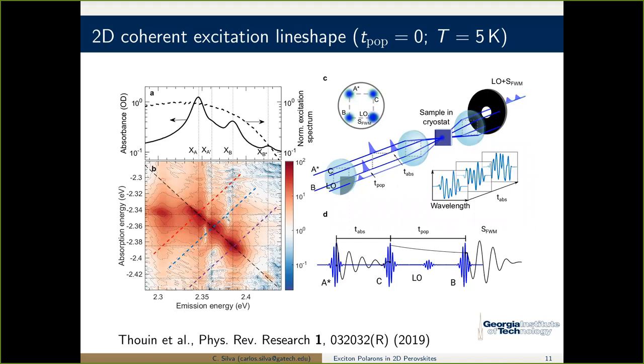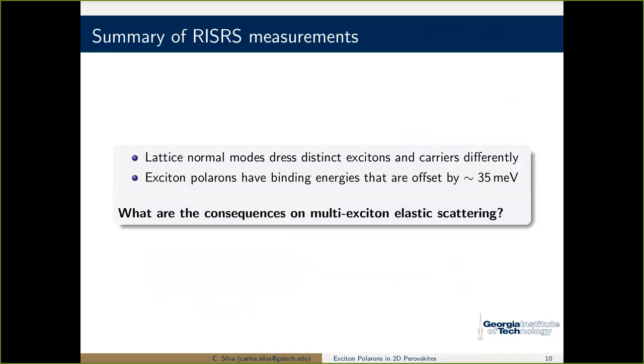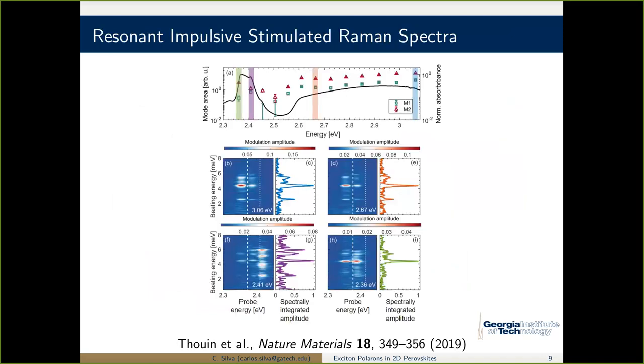Hear you. So going back a little bit with your pump probe, often when you're pumping, you end up in high carrier density regimes. Right. So does that affect in any way the exciton populations? There will be a relaxation process. If I didn't throw away the population dynamics in my pump probe spectra, you do see that.